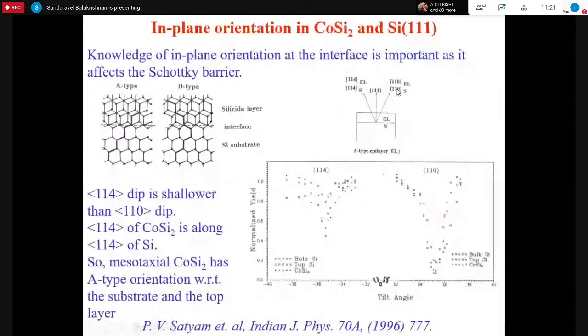We look at this signal for both substrate and epilayer. Suppose these dips follow the same thing as the substrate, we can tell that there is no rotation. For example, in our case, if we see this for both epilayer as well as substrate, we see deeper dips along the 110 direction and shallower dips for 114 on the other side. So it is A-type cobalt disilicide. If there is rotation, then whenever 110 is deeper, at that place you may be getting 114.